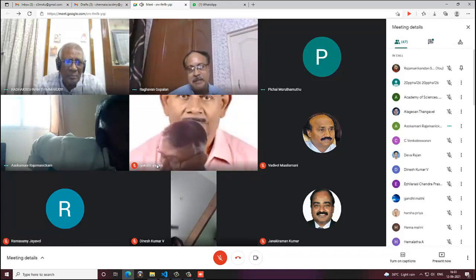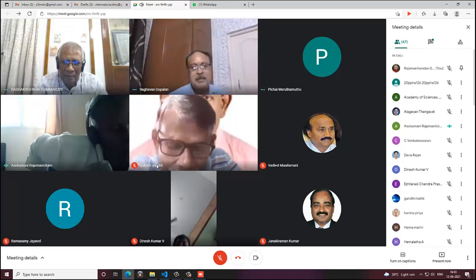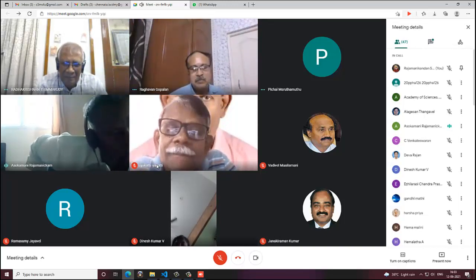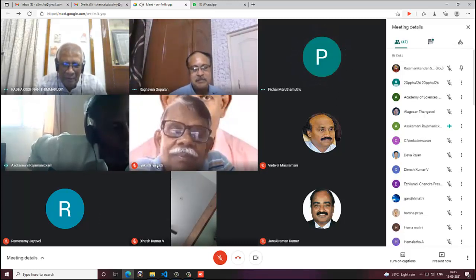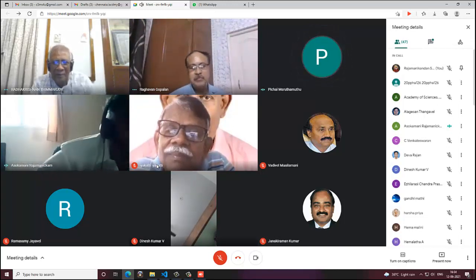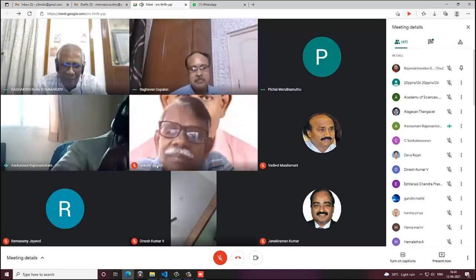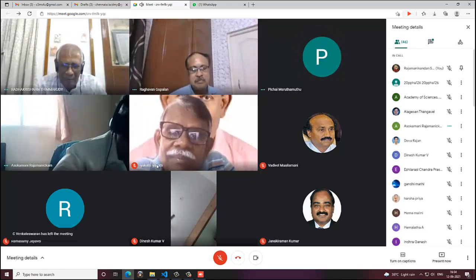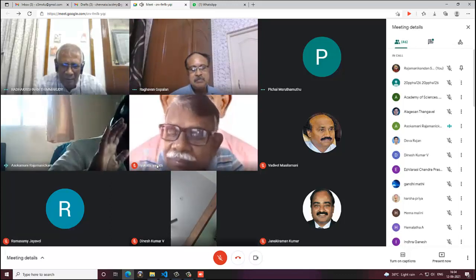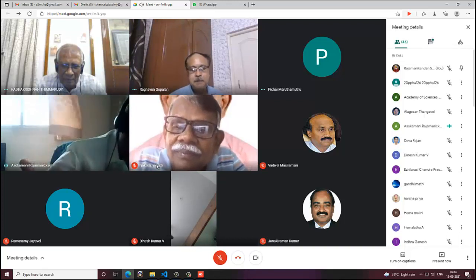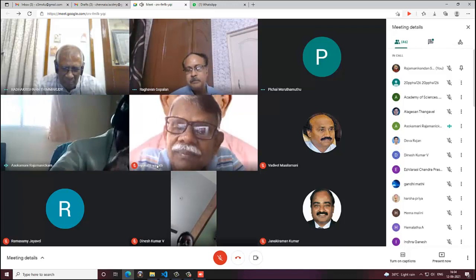When you go to higher and higher Tc, the coherence length becomes shorter. The coherence length is nothing but the size of the Cooper pair. And 2 delta by kTc is not equal to 3.52 as BCS thought. One important point I want to make: if you take an elemental superconductor like ruthenium or zirconium, the isotope coefficient is 0. There is a very big question which has been raised by somebody. I wrote a letter and he wrote a reply. There is a paper by Hirsch who attacks the BCS theory, saying that even for elemental superconductors BCS theory is wrong, because the isotope coefficient is 0 instead of 0.5. Something is wrong somewhere.